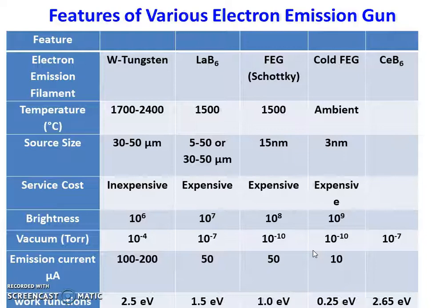The emission current required in microamperes is 100 to 200 in the case of tungsten based, and it is minimum in the case of cold FEG, which is 10. The work function for these electron guns is 2.5 electron volt for tungsten based, 1.5 for LaB6, 1 for FEG, and 0.25 for cold FEG. In the case of CeB6 it is 2.65, which is the highest.